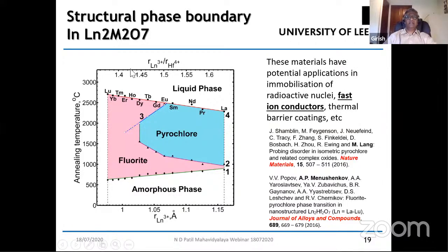This is the radius ratio of the lanthanide ion to hafnium in this case, but the same thing applies to zirconium as well, because we have worked on both materials. If you plot the same map for the lanthanide ionic radius to zirconium ionic radius ratio, then again around 1.46 to 1.48, fluorite transforms into pyrochlore and vice versa. This is an interesting structural property, and as a result, this material is quite flexible in a number of ways, for example in ionic conductivity, or in accommodating ions of different sizes in the structure.